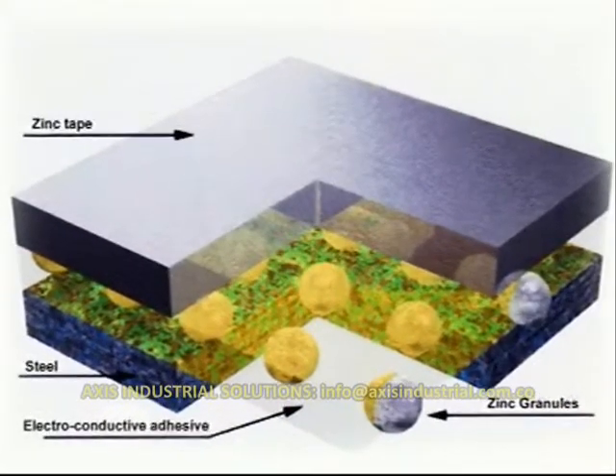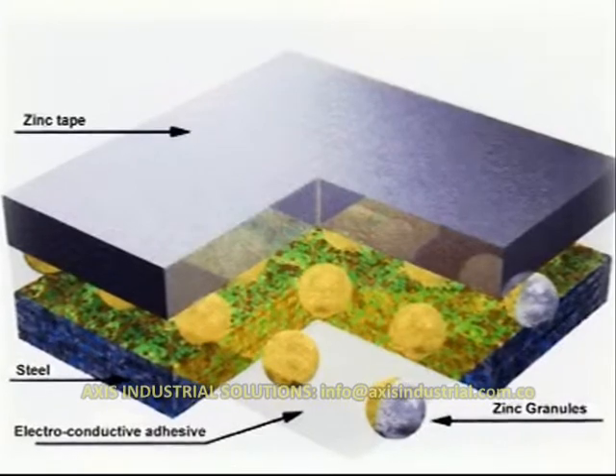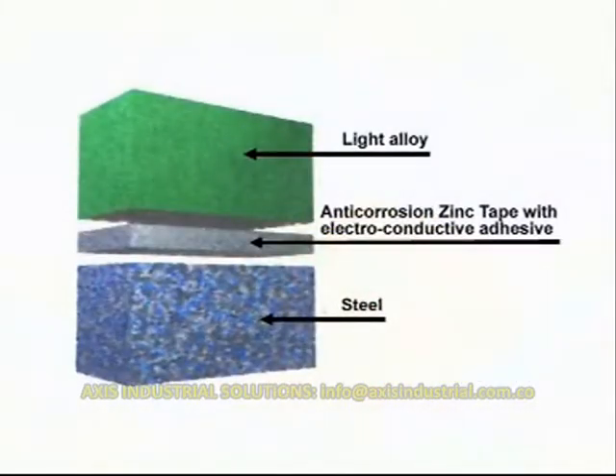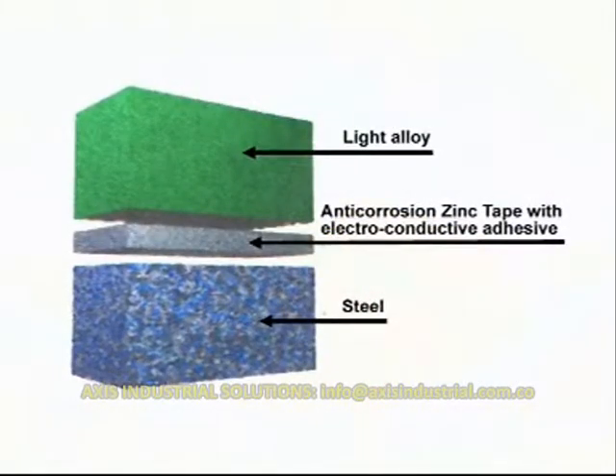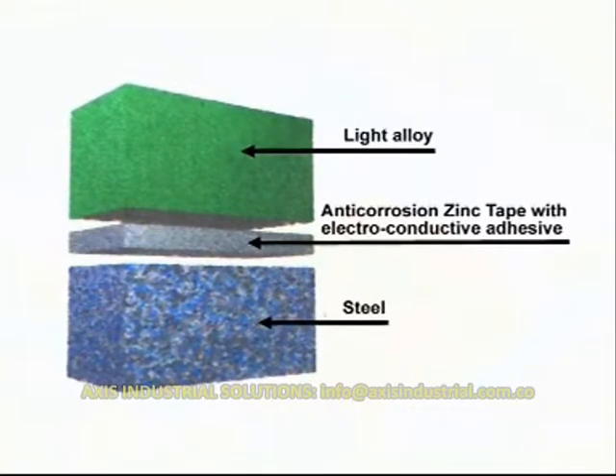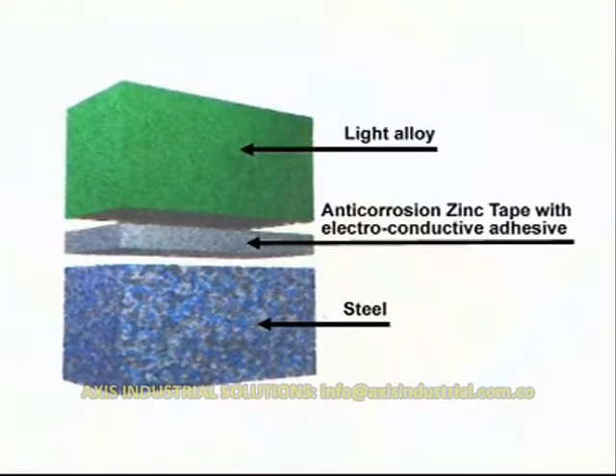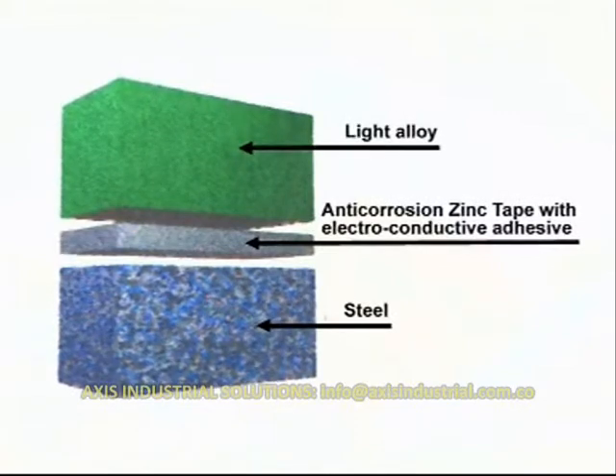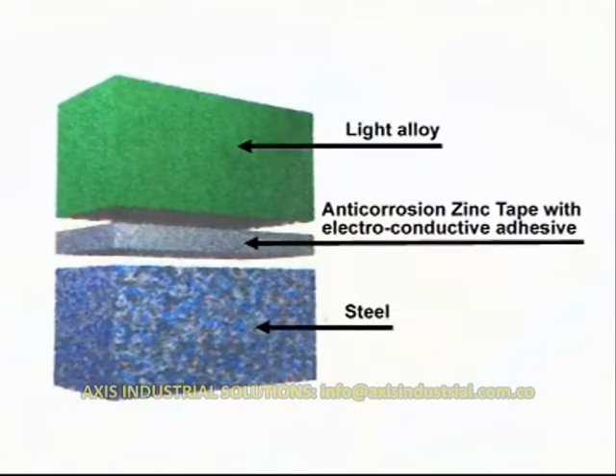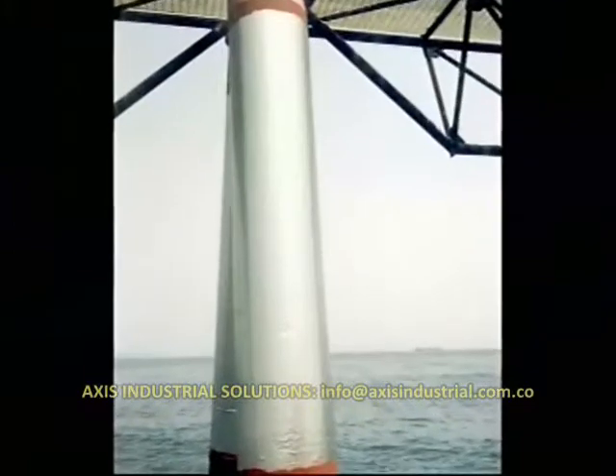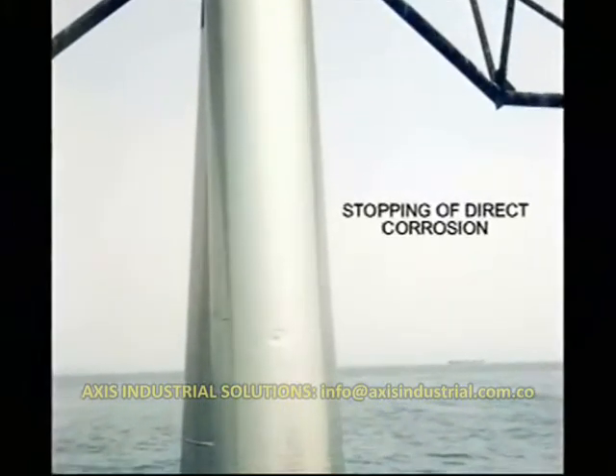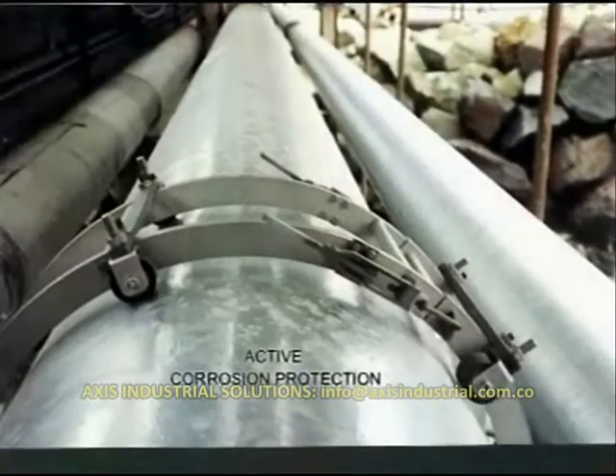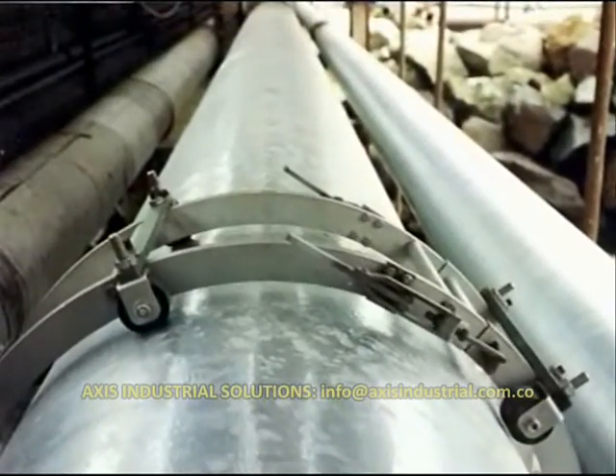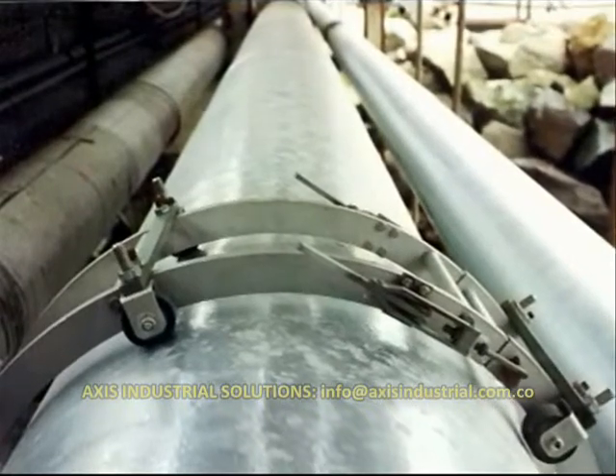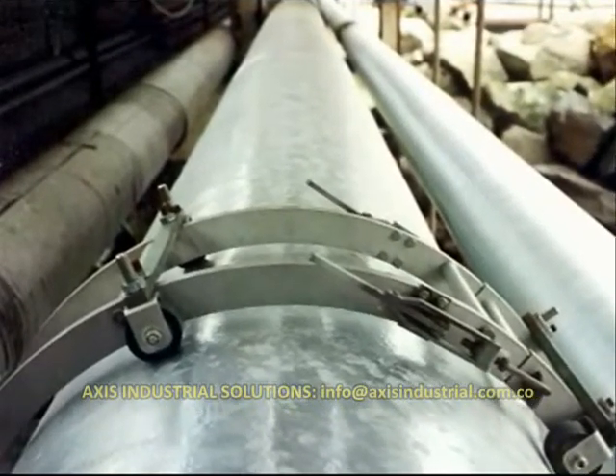As a consequence of the unique manufacturing process and the high purity of the zinc, the foil is totally homogeneous and has an isotropic microstructure which cannot be found in other protection systems. For this reason, the corrosion process is suppressed with no pitting or any form of local corrosive attack. The product's main features include the stopping of any direct corrosion, active corrosion protection. This is due to the electrical contact between the surface to be protected and the zinc layer, which in the presence of an electrolyte reacts as a sacrificial anode.